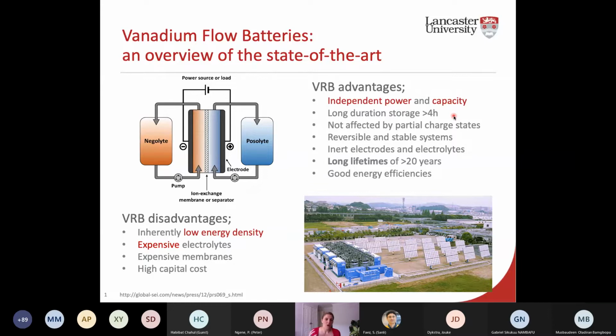Because there are no significant phase changes, going to the gas phase or going to the solid phase, which is particularly destructive, you have possibly more than 20 years of cycling back and forth available without damaging or reducing the efficiency of the battery. It sounds fantastic, but there are disadvantages too.